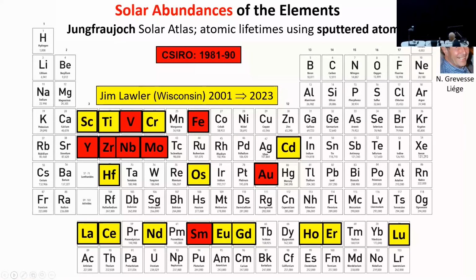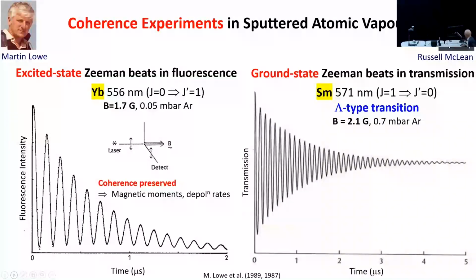And why we could do this to such high accuracy is we could measure these lifetimes very, very quickly. In less than a minute, we could do a whole element in a day, maybe 50 different levels. And then when determining the solar abundance, you plot a curve for a whole lot of different transitions. And if there was an outlier, that would mean there'd be a blend in the solar atlas, and you could discard it and so on. And this way we get very, very accurately the solar abundances. Again, we got sick of that, moved on.